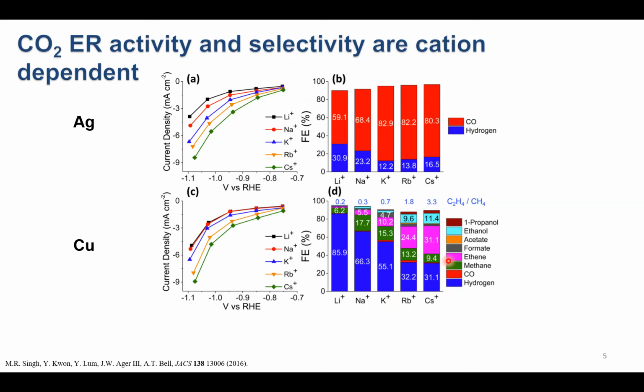If we look in particular at ethylene, shown here in purple, we can see that we have a much higher selectivity to ethylene with cesium, actually 21 times higher selectivity with cesium in our electrolyte than with lithium in our electrolyte. And so if we want to produce ethylene, or some particular product, we can tune electrolyte composition to increase activity and selectivity, but we need to understand the mechanisms of this effect to really take advantage of it. So this is something we want to understand at the atomic scale.